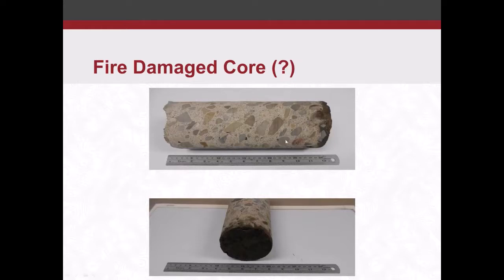This core was actually taken from the surface that had the indirect exposure, so it was the west face of that north pier. And this is just a bunch of grease and stuff that has built up on the surface of the concrete. In my opinion, this is the reason why the data on that face was jumping all over the place. I don't think we were able to get good quality data because of the anomalies on the surface. Again, this is not fire damage here. This is an oily, greasy substance that soaked into the surface of the concrete. It's a byproduct of the environment that the concrete is in. So this is not a fire damaged core. This is not what a fire damaged core looks like.